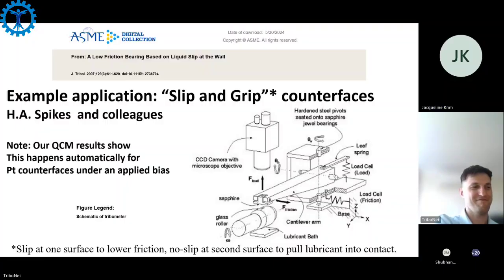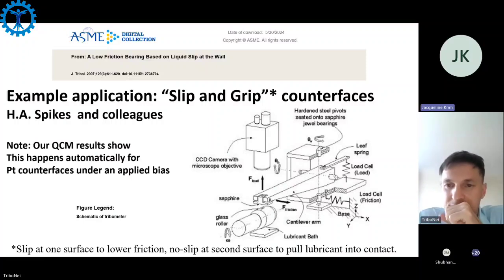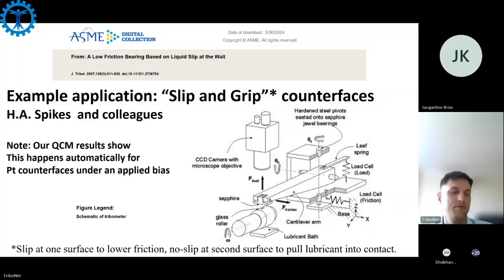Okay, slip and grip. If you know that your lubricant is going to be very slippery, that's good. It'll reduce the friction. But it's also bad because your lubricant might not even make it into the contact. It's so slippery. So Spikes has demonstrated that by having a non-slip on one counterface, it can be pulled into the contact and then the friction is low. So that's one way, and the QCM can show that this can happen automatically by moving particles. You can deposit a film and get high friction. Okay, next slide.